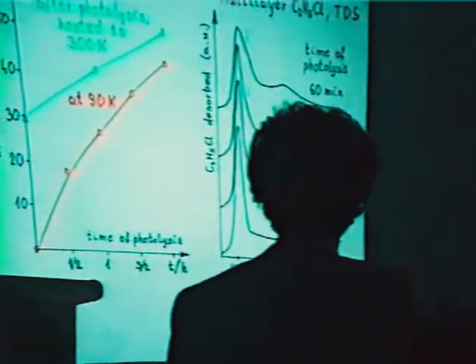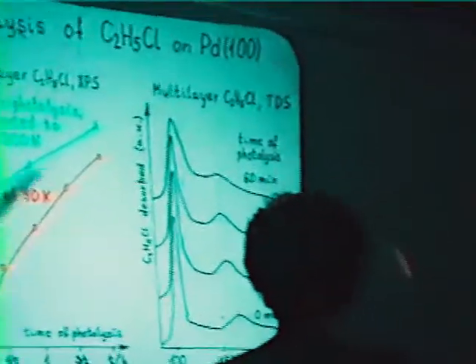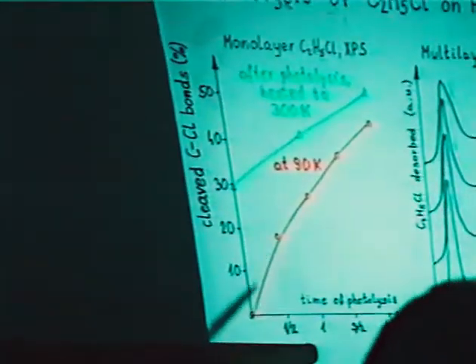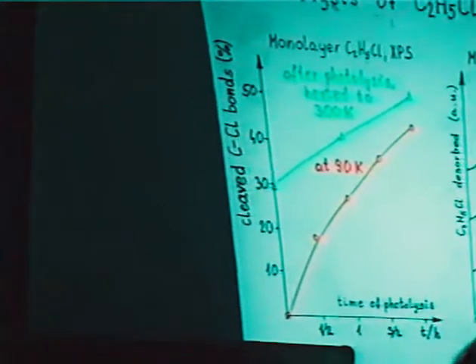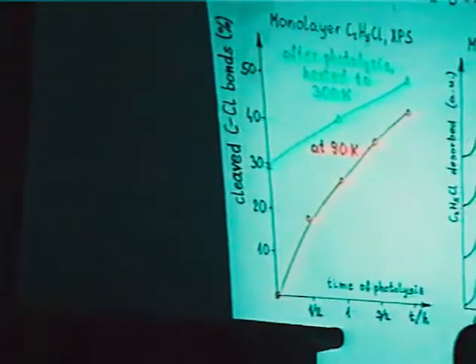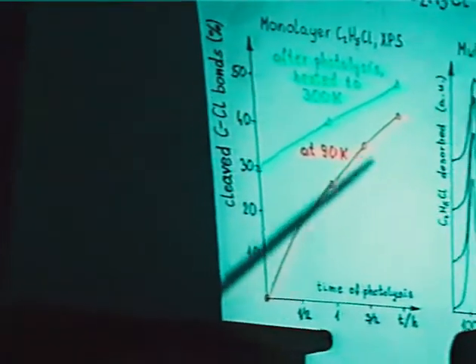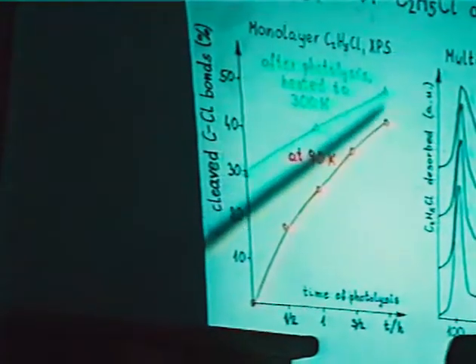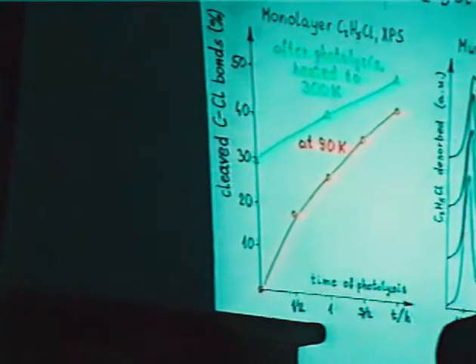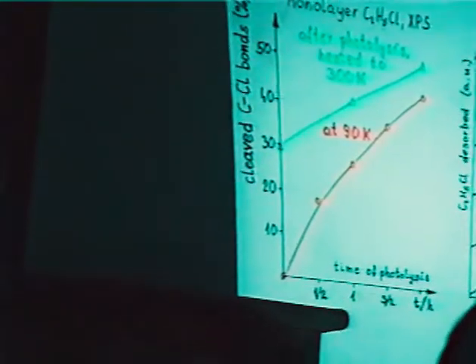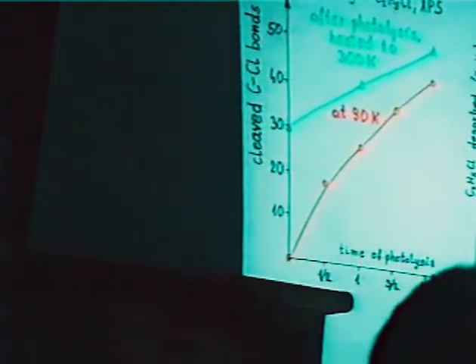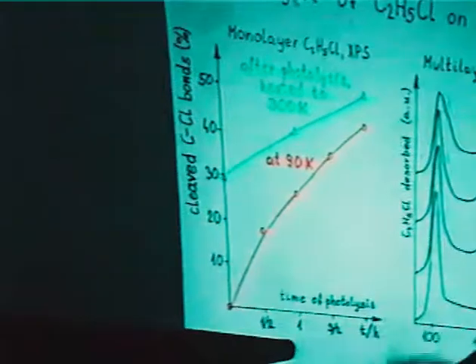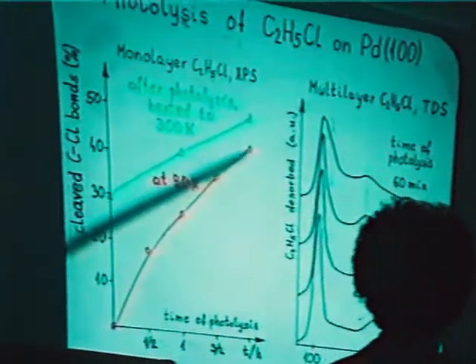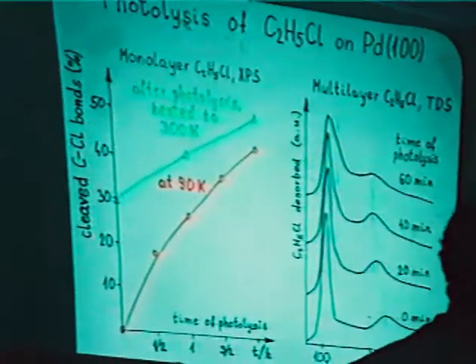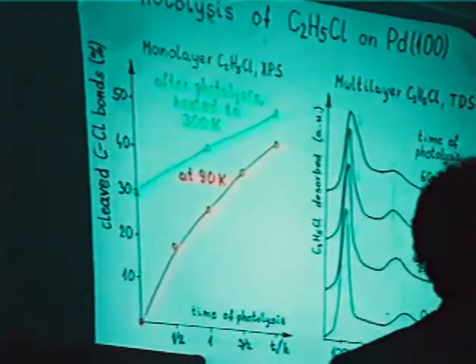At 90 K, the photolysis can be achieved easily, and we can see that as the photolyzed layer was heated to higher temperature, some additional thermal decomposition occurred. The products of photolysis cannot block all sites required for the thermal decomposition.